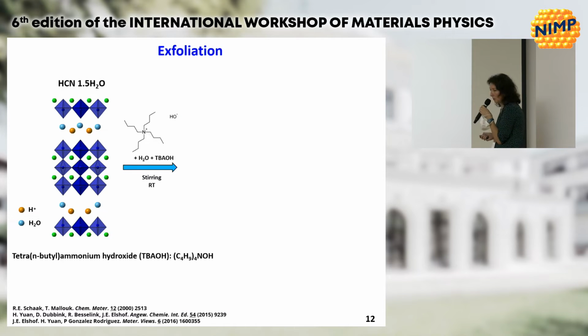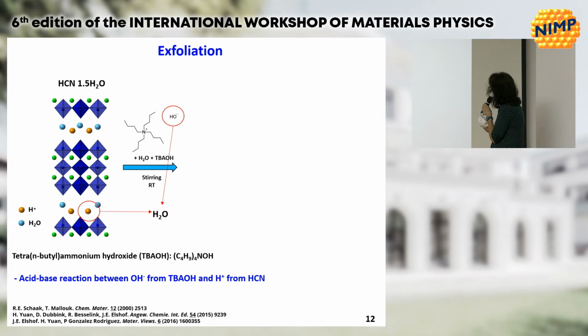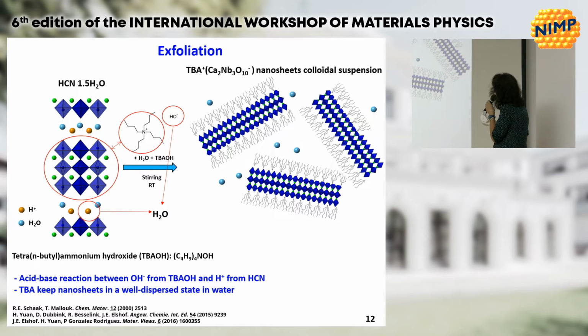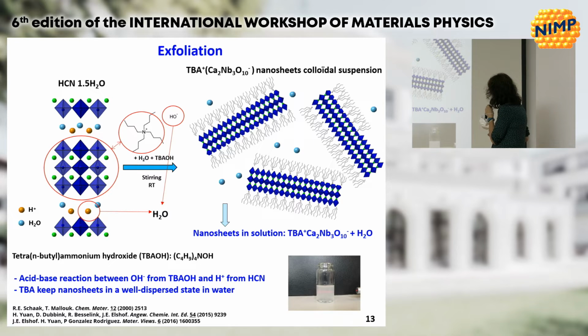So the second step of the exfoliation, this is the real exfoliation, is to put this powder now in another liquid containing water and tetrabutylammonium hydroxide. And we have here a reaction between the OH- ion of this ammonium hydroxide with the protons of the material, and both form water, and then the crystal falls apart to form nanosheets, which are negatively charged, and they react with the TBA+ to form this colloidal solution. So at the end, we have a colloidal solution of the nanosheets in this bottle.